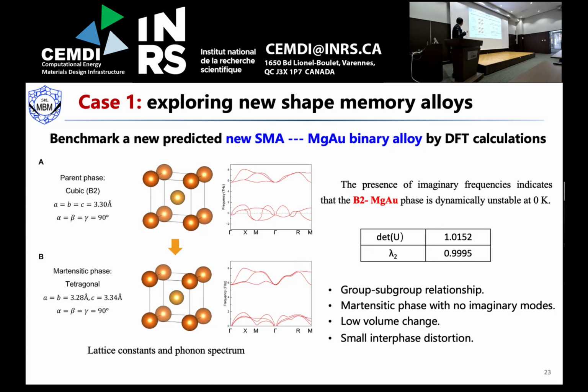And we found that the parameters at the martensite change from the B2 to tetragonal. This is obviously a group-subgroup relationship. From the phonon spectrum, we found the martensite didn't have any imaginary mode. That means the martensite is stable. And we also calculated the volume change, and this volume change is very small. So this kind of transition, the volume change is also very small.